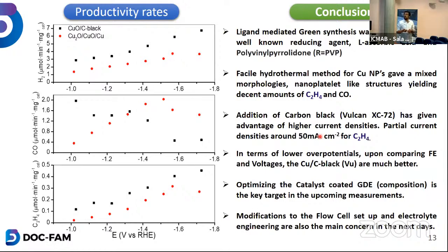In terms of low overpotentials, the carbon black, because of its high conductivity and high current densities, gives lower overpotentials when comparing Faradaic efficiency and voltages in these carbon black copper composites.